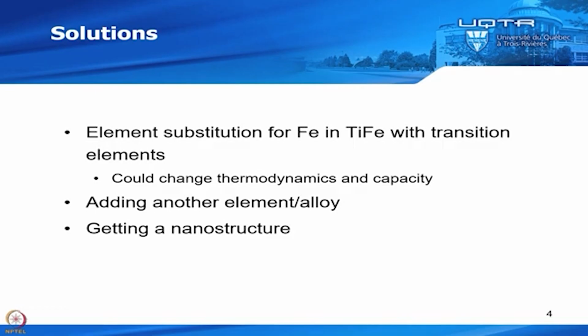Well, you could substitute some element. Usually people substitute on iron. So they replace iron by other transition elements, for example, manganese. And then you could have a first hydrogenation that is quite quick. But when you do that, you could change the thermodynamics and the capacity. So that's not the ideal way. Or you could add some other element, or add another alloy, and have a nanocomposite. Or you could get a nanostructure. So this is what we will see in this talk.